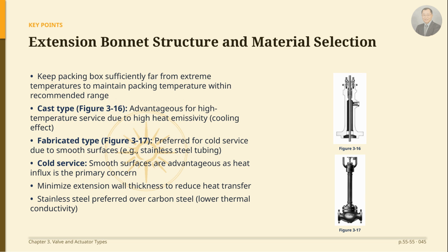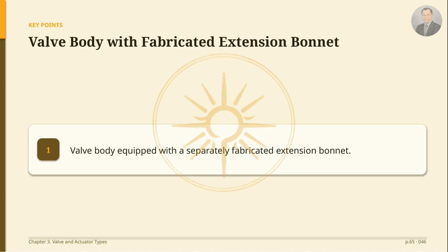The cast extension in Figure 3.16 is advantageous for high-temperature service because its higher heat emissivity provides a better cooling effect. Conversely, smooth surfaces, such as the fabricated type made from stainless steel pipe in Figure 3.17, are preferred for low-temperature service, as the primary concern there is preventing heat from entering. In either case, the wall thickness of the extension should be minimized to reduce heat transfer. Additionally, stainless steel is generally preferred over carbon steel due to its lower thermal conductivity coefficient. This is a view of a valve body equipped with a separately fabricated extension bonnet.